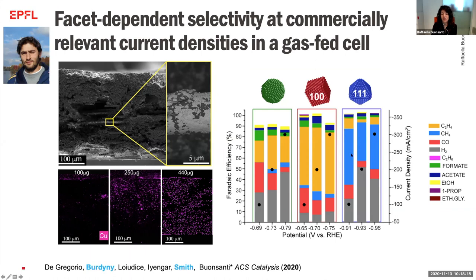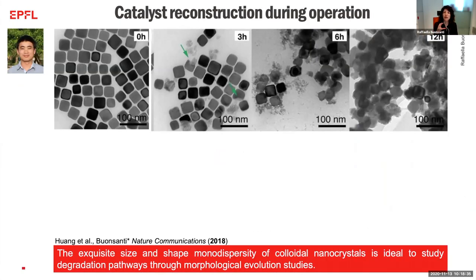Instead, this result told us that playing with the catalyst design is important even when we move to this commercially relevant high current density. Now, another possibility that these uniform nanocrystals offer is that, because they are so monodispersed in size and shape, they are also a beautiful platform to study reconstruction of the catalyst while the catalyst operates.